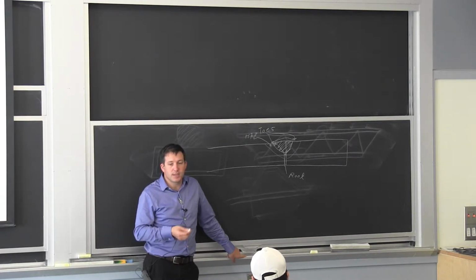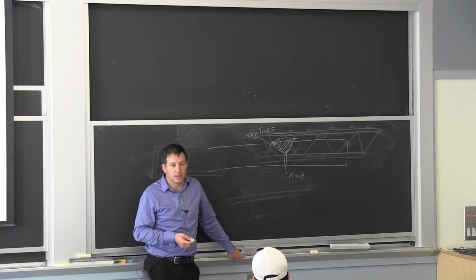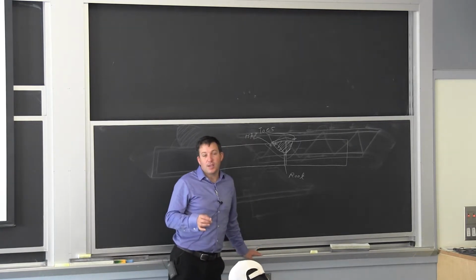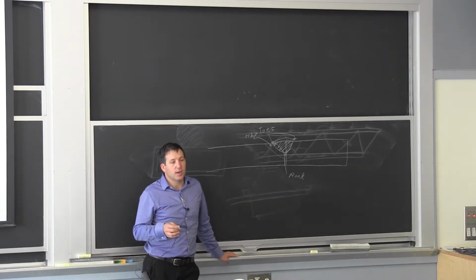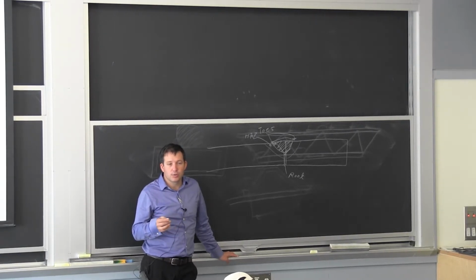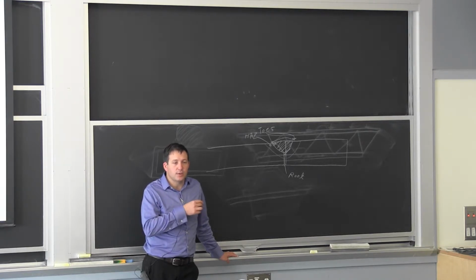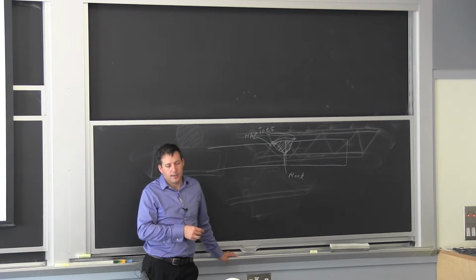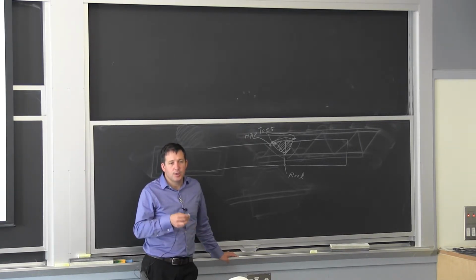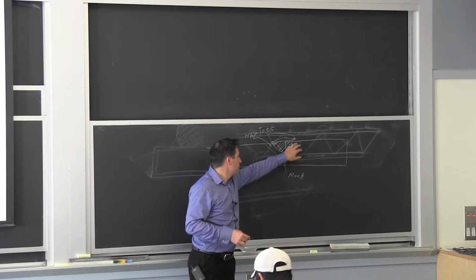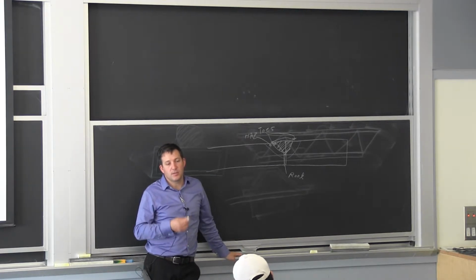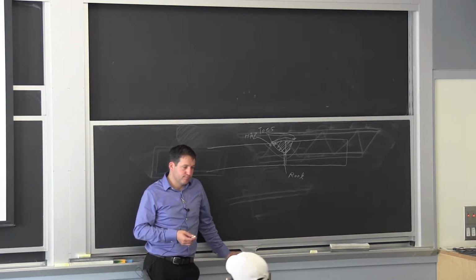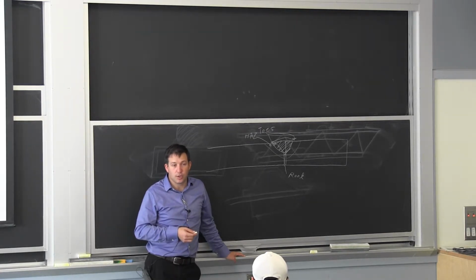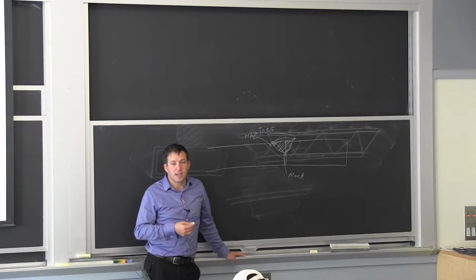And if you remember with steel, what I said is you quench and you're going to form a hard phase. You're going to form martensite. It will happen if you have some alloying element in your steel, if you have high carbon. If you're using a very typical structural steel, it's not bad, because if you remember, you have to quench quickly to reach that martensite. So if you have an alloy that is essentially plain iron and carbon, low carbon content, you can reach this low temperature state without transforming to martensite. It's going to be a very small transformation. Maybe you have a little bit of a strengthening effect because you were cooling quickly. So you're going to have a fine pearlite, for example, but it's not going to be too hard.